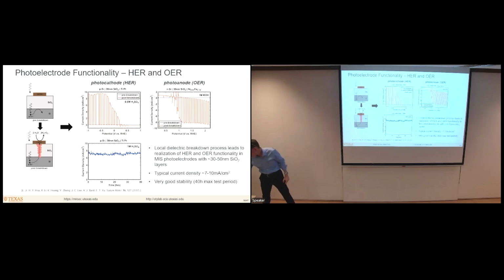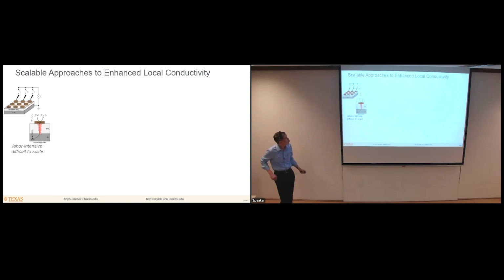Now, the challenge here was that to actually make these structures required a heroic effort on the part of the student who was working on this, because for each photoelectrode device, you have an array of these catalyst pads, and they have to be electrically broken down one by one. So for every device that Li made, he had to do this like 1,000 times. This is not scalable at all. It was sufficient to get a nice paper out of it.